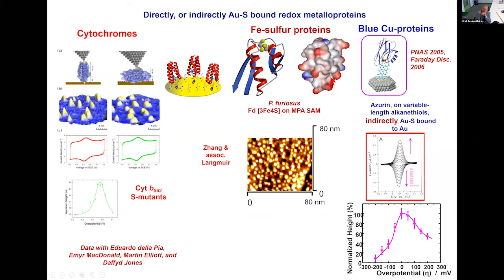Here, you can see single molecule resolution for the ferredoxin. And here again, we have the blue copper protein azurin. It feels very comfortable if it is immobilized on a self-assembled monolayer of alkanethiol. You can see it responds so nicely with very pretty voltammograms, and it also gives a tunneling spectrum, as we have just seen we would like to see.